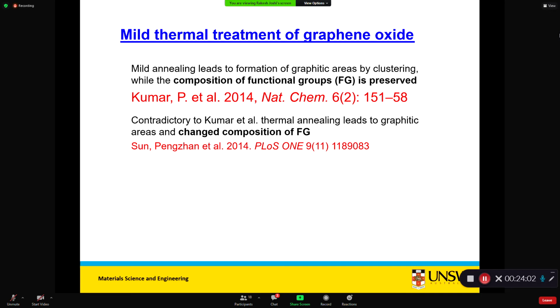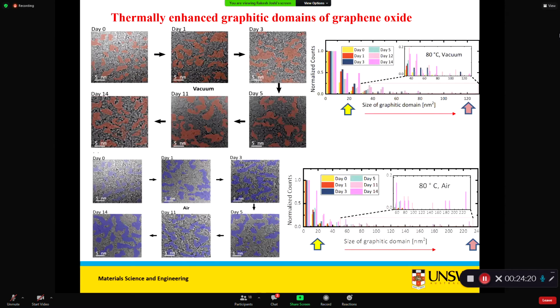The objective was to see if we can enlarge the graphitic domains, because graphitic domains offer frictionless flow of water. So we can also reduce the porosity and have a higher water flux. Then we conducted experiments and did extensive TEM studies. This is 1.5 years of work. We annealed pure graphene oxide. This is the day 0 sample, meaning the unannealed sample. This one is in the vacuum, and this one is in the air, different conditions. The air one was the Nature Chemistry method, and this is like Hongwei's group in Tsinghua.